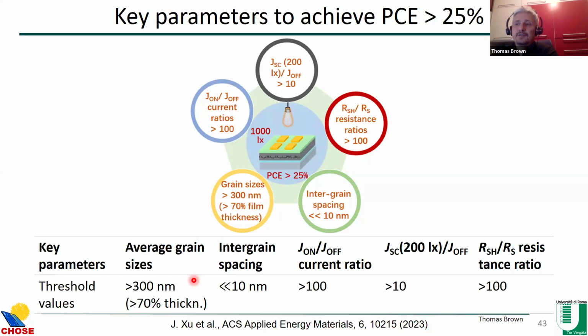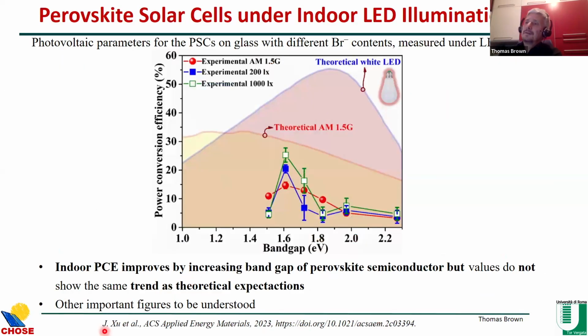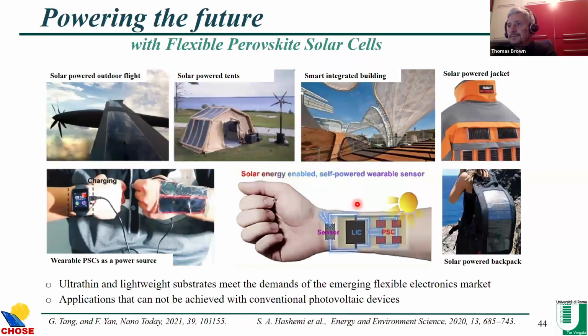Intergrain spacing needs to be much less than 10 nanometer. The J on over J off needs to be greater than 100. And the shunt over series resistance ratio needs to be higher than 100. So that's the reason why you don't get the highest efficiency here: for high bromide content, you start to get defects arising in the film, which lower the efficiency.